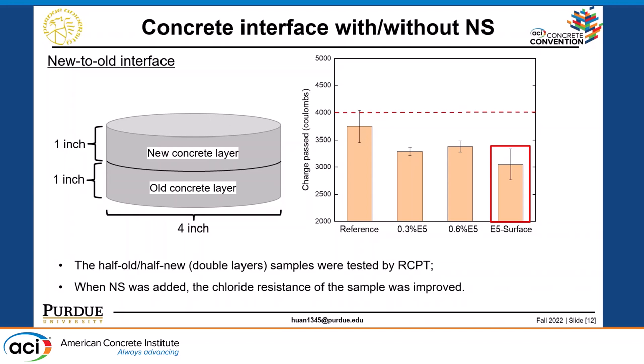We have the old layer, we have the new layer, and we want to see how the interface changes. Under RCPT testing, we notice the charge passing through the sample was decreased if we have nanosilicate in the sample, meaning less chloride ions penetrated. So with nanosilicate in the concrete sample, we can have better chloride resistance, especially at the interface. We observed the surface method performing even better than the direct adding method. We believe this was due to the precipitation of nanosilicate creating a denser and more compact interface between the layers, blocking the penetration of chloride ions.